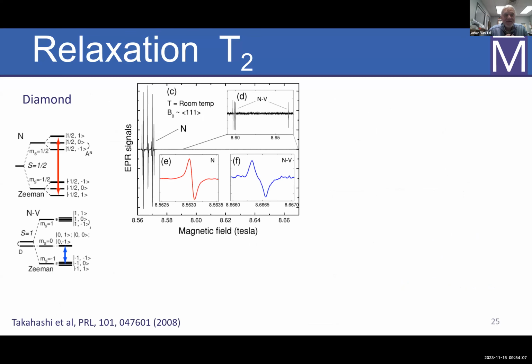So then later on, with Susumu Takahashi, who is now at the University of Southern California, we looked at this a little bit in more detail over a larger temperature range, and we looked at nitrogen centers. So these are either P1 centers, which are just nitrogen substitutions in diamond, and NV centers. So this is the P1 center signal, and then these small signals out here, that you have to blow up quite a bit to see them, are the NV centers.